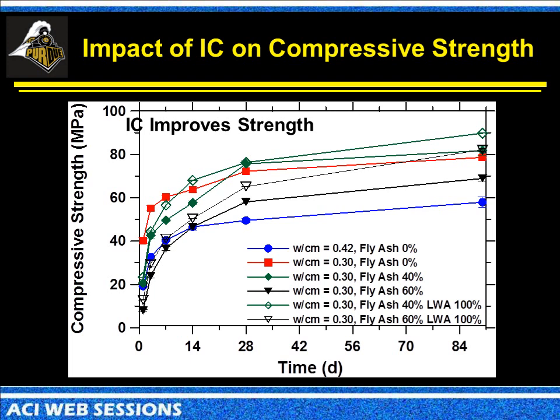What I was surprised at is we saw a slight increase in the strength. The reason for this, even though we're putting in a particle that may have a slightly lower strength for those internal curings, is that we're getting increased hydration taking place. So we're essentially more efficiently using the cement and the fly ash that are there, because we're supplying enough water that the reaction can actually start to take place.